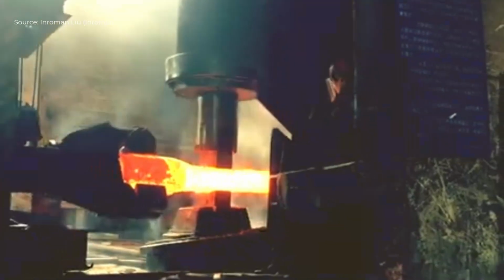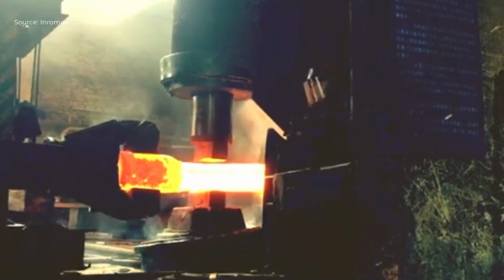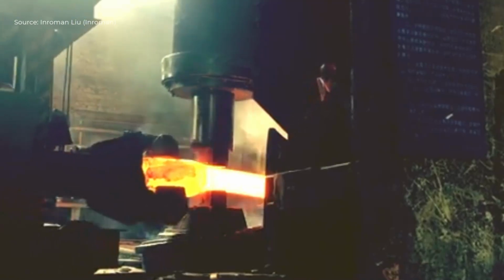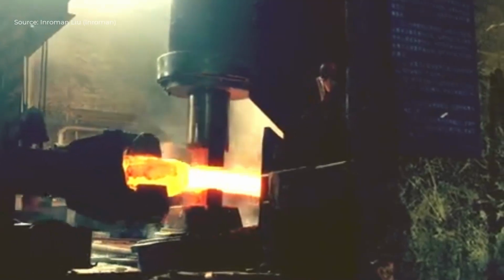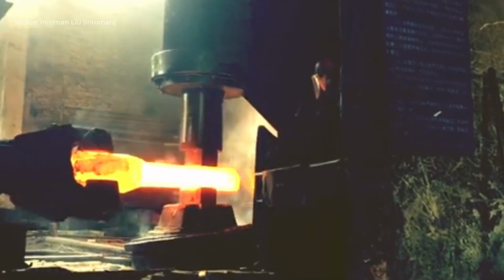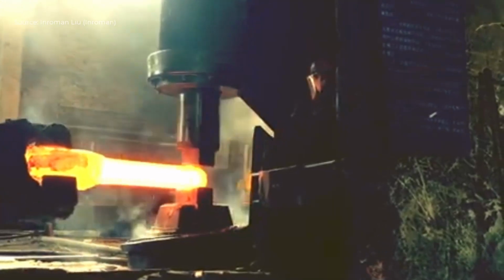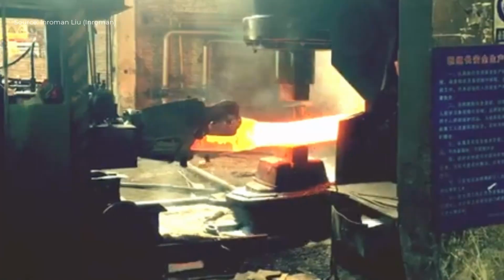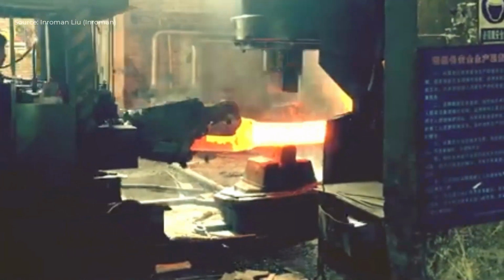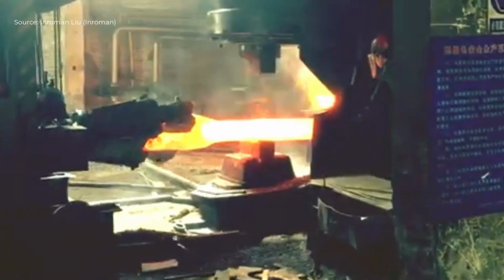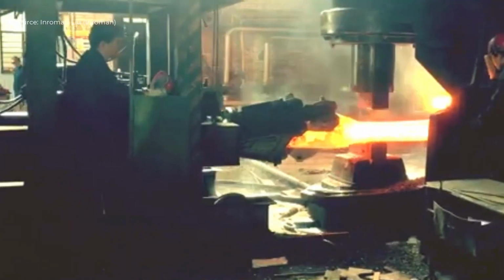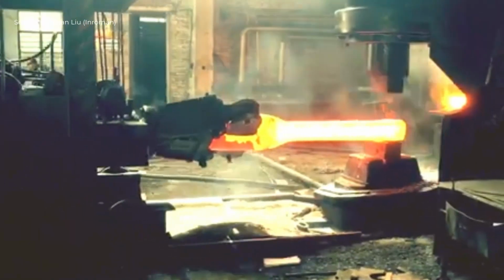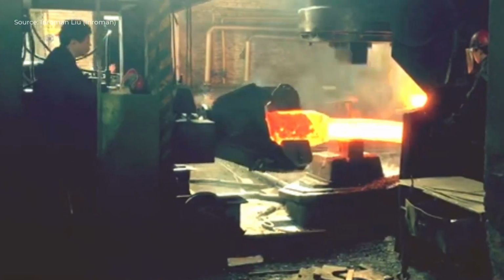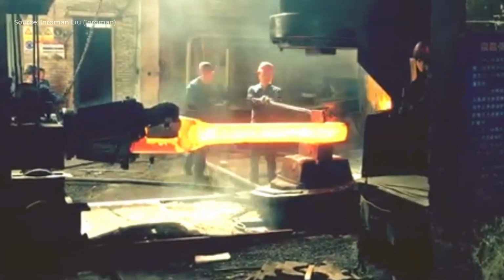After achieving the desired billet dimensions, the billet is reheated and undergoes preform forging. In this stage, the billet is forged into a near-net shape, resembling the turbine blade, including the root and airfoil profile. Large hydraulic presses apply controlled force to shape the material gradually, maintaining optimal temperature to prevent defects. The forging dies may be flat or feature rough cavity shapes to guide the material flow effectively.